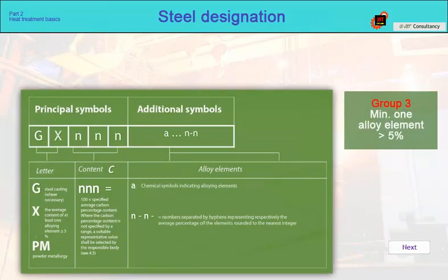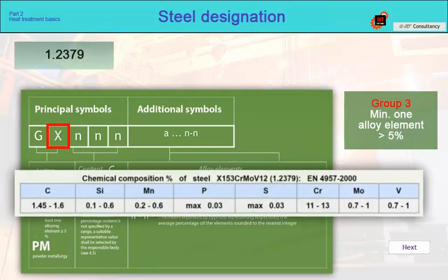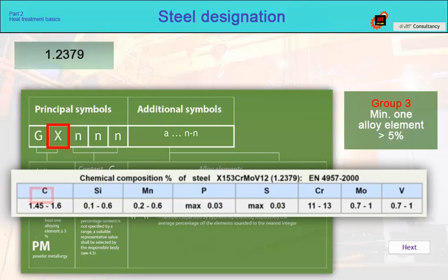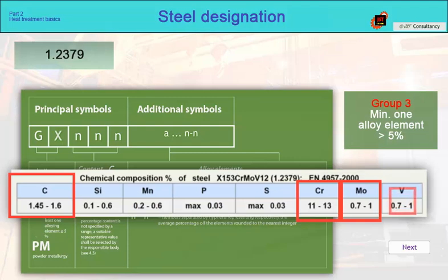The third category of steels are high alloy steels with a minimum content of at least one element over 5%. This series of steels is defined by the letter X. This letter may be preceded by the letter G for cast steels or PM for powder steels. For example, today's frequently used steel 1.2379. Its chemical composition is approximately 1.53% carbon, 12% chromium, molybdenum 0.9%, as well as vanadium.